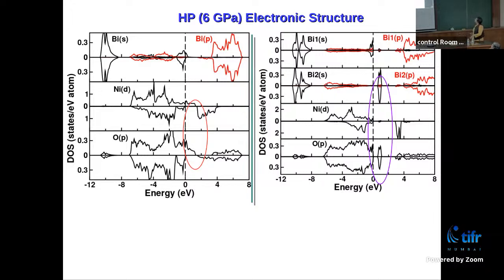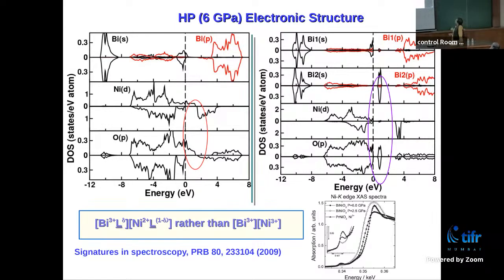Just as a comparison, I flash again the ambient pressure electronic structure. You had this split of state, which looked very much resembling the split of state of the oxygen. In the high pressure, you do not have anything on bismuth, rather you have nickel, and the whole thing has become metallic. This was insulating, and the empty nickel states look very much like the oxygen empty state. So therefore, the high pressure electronic state, instead of nickel 3+ which it doesn't like to have, is nickel 2+ with the ligand hole and nothing on bismuth.